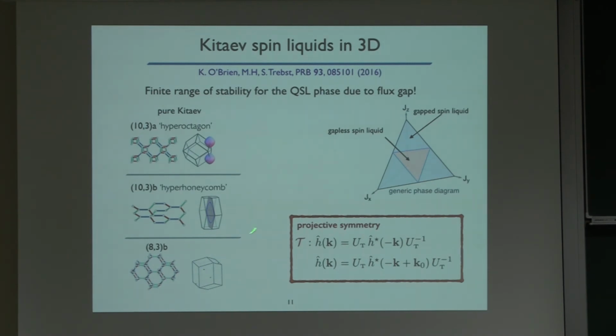If you want to have Weyl nodes, then you need an additional symmetry. In this case, it was inversion symmetry that basically tells you that this Fermi surface up here is not stable. In fact, only point nodes can be stable.